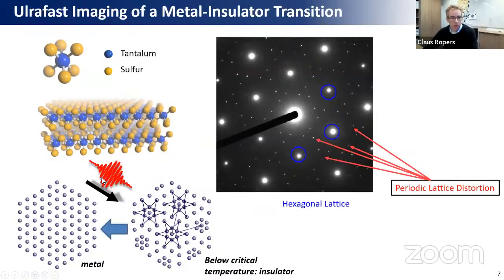So if we now want to study the transition of this material from this low temperature insulating phase to the high temperature metallic phase by optical excitation, what we need to do is again do an optical pump and then electron probe beam and then record these diffraction patterns as a function of delay.